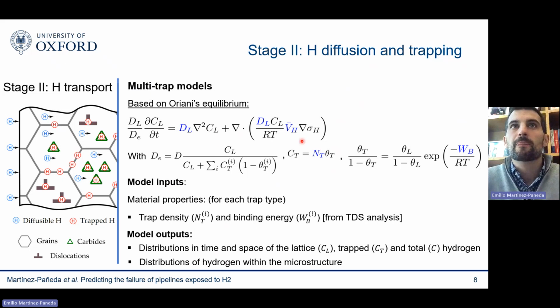So basically, you need these two properties in addition to the ones we discussed before: a trap density and a binding energy. Those will come from TDS experiments. And there's a little bit of uncertainty in there, but more or less, they're relatively well understood. And I think the good thing here is that because pipelines are exposed to hydrogen for a long time, we do get a steady state situation pretty quickly, after 2 or 3 days. And these pipes are going to be exposed to hydrogen for decades, right?